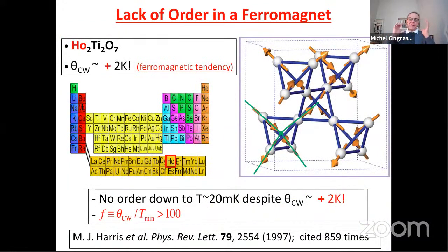So the discovery of spin ice was a complete accident. Steve Bramwell and Mark Harris were investigating this holmium titanate compound. They knew from magnetic measurements that below 1 Kelvin the holmium was very much Ising-like in its response. But they also knew from the magnetic measurements that the Curie-Weiss temperature was about 2 Kelvin, with a positive sign, meaning that it is ferromagnetic-type interactions that are operating in this compound.